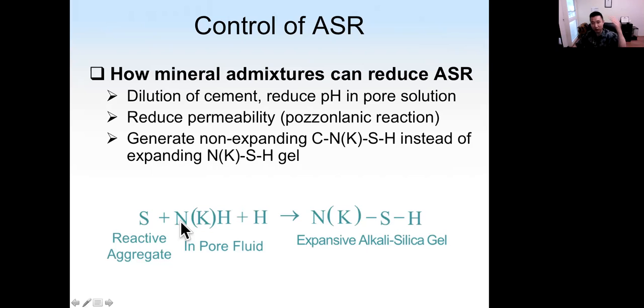Mineral admixtures are very effective to reduce ASR. But of course, we need to mix mineral admixtures in fresh concrete. Okay, so before ASR occurs. The reason for that has many different folds. The first fold is mineral admixture will reduce alkali concentration in cement, so that will dilute cement, reduce the pH level in pore solution, to reduce the amount of alkali.